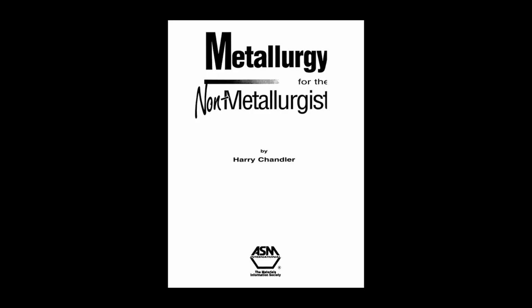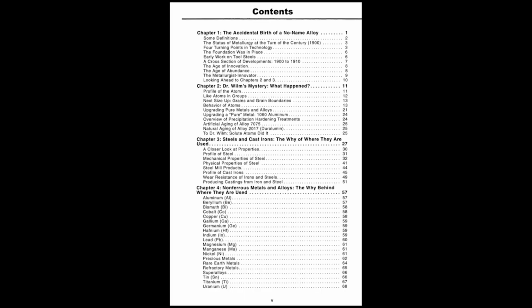Okay, makes sense. What if you only want the surface to be hard? Like for gears or bearings? Oh, that's case hardening. Techniques like carburizing or nitriding diffuse elements like carbon or nitrogen into just the surface layer of the steel at high temperature. Then you heat treat it so only the outer case becomes hard, while the inner core stays softer and tougher. Gives you wear resistance on the outside, but the part can still absorb shocks. Clever. Now, the outline mentioned some diagrams.